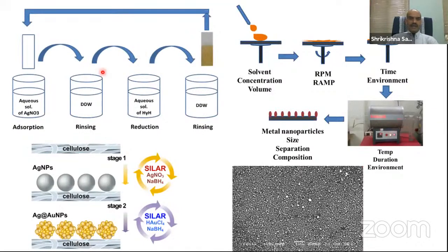So what we did in our laboratory, and of course there are many approaches people have used, but I'm going to discuss very briefly our approaches. We use the successive ionic layer adsorption and reaction method, and spin coating. The advantage is that we can put the substrate on which we want to grow these metal nanoparticles. For example, if I want to grow silver nanoparticles, I will immerse the substrate, which can be glass, cotton, paper, or anything, including any flexible substrate.